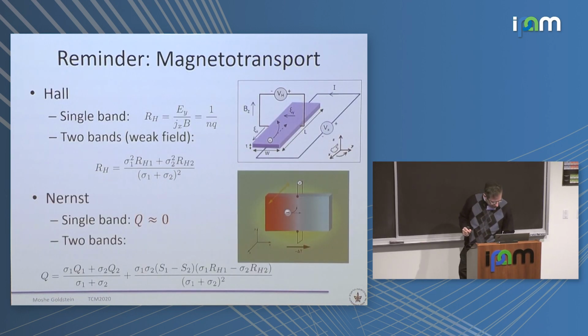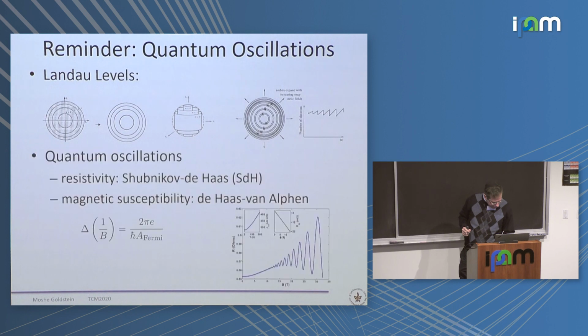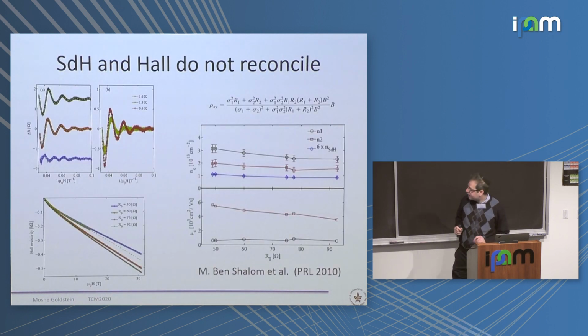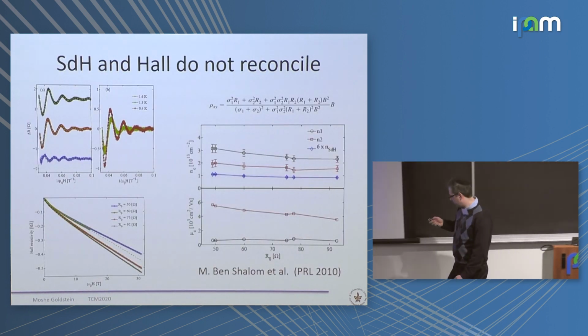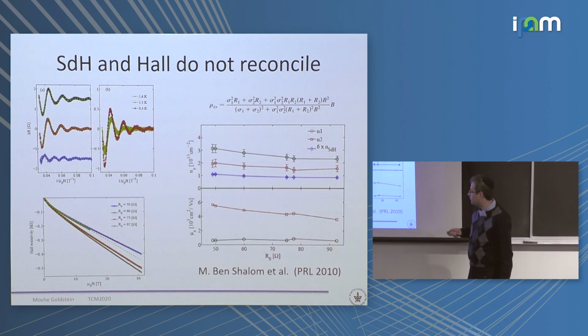And okay, to understand more, you need to do some more sophisticated measurements. So my colleagues have done, other groups as well have done Shubnikov-de Haas measurements, so magnetic oscillations, and also low field Hall. And usually if you have a single parabolic band, then the Hall resistance, you can get from it a Hall number, which is some proxy of the electron density. So again, for a single parabolic band, it would be the electron density.